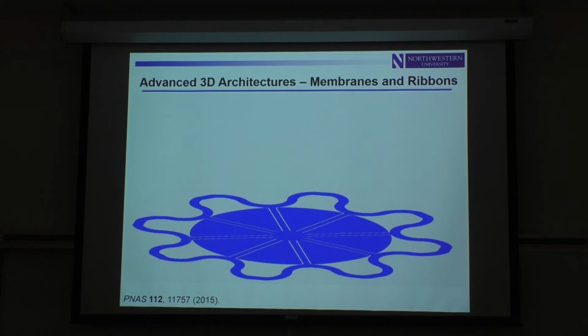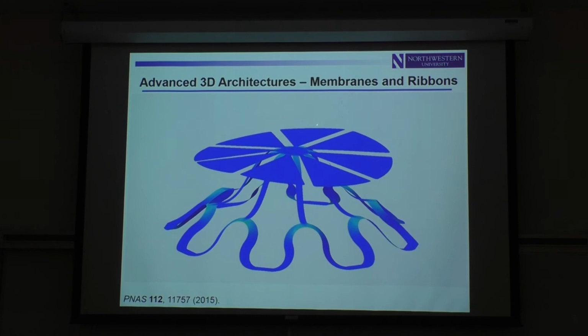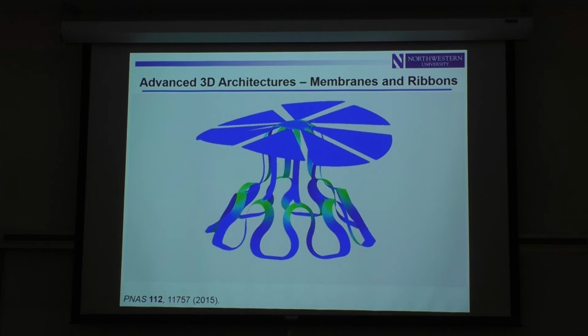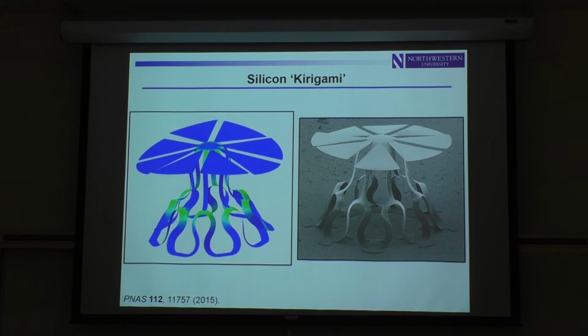This is kind of an odd structure. This is the 2D precursor. It might not be immediately apparent what that's going to transform into upon release of the pre-strain of the substrate. But in this case, it really sort of grows up out of the substrate and involves several levels of buckling up out of the plane to form some kind of sunflower jellyfish type structure. Anyway, there's a huge design space here. That's that structure in silicon. There it is in modeling results.